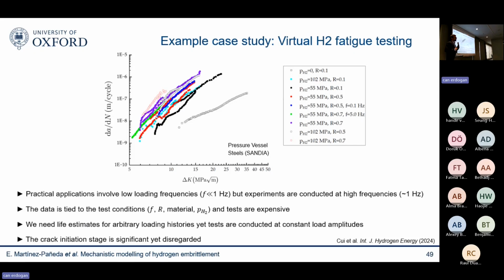And this data has some issues as well. That's why industry partners approached us with this. One issue is that there's a frequency effect. Normally in fatigue, we don't care about frequency. But the moment you have hydrogen, if you load very slowly, there's more time for the hydrogen to accumulate. But if you load very fast, then the hydrogen doesn't have time to move. So there's a frequency effect. And we know that the slower we load, the more susceptible we're going to be to hydrogen embrittlement. So you want to run your experiments at the frequency of your application. But the application involves very low frequencies, and these experiments are very expensive, so we run them at high frequencies. So we're being non-conservative, and the industry is worried: what is the error that we're making by running experiments at very high frequency?